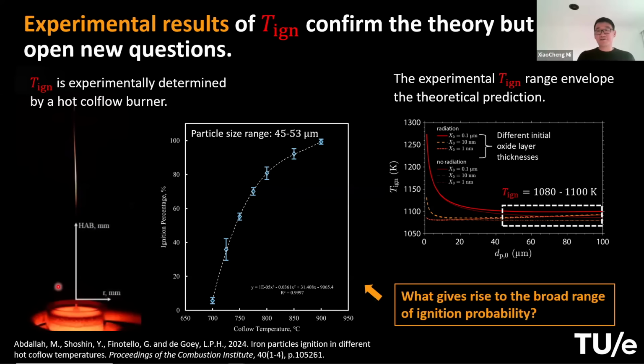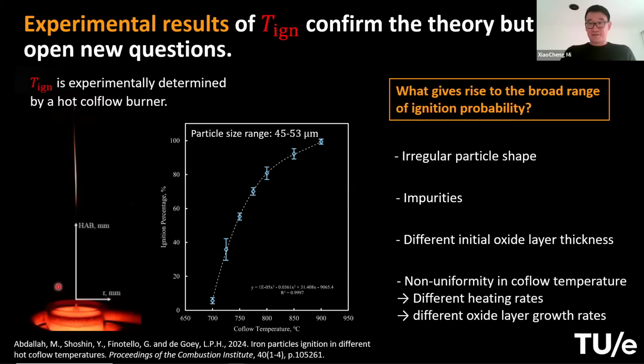But the thing is, theoretically it only tells us there's a single value of ignition temperature, but experimentally it tells you a large range, right? So what gave rise to this range of probability? There are multiple factors that we are considering. First of all, the particles are not spherical, they're irregular and could also be partly porous. Also the particle may contain impurities, which change its chemical and thermodynamic properties. Of course, the particle may have different initial oxide layer thicknesses. And the last one, maybe the most relevant to the larger scale combustor, is that the co-flow heating around the particle might be different. So the particle may experience different heating processes as it goes across this flow field. This I will elaborate further.